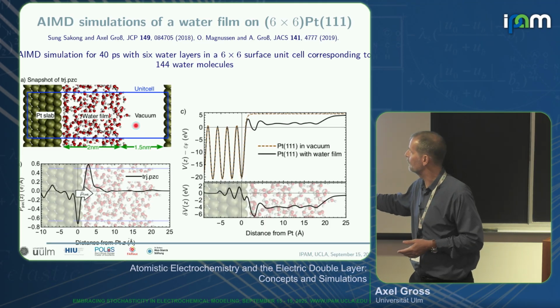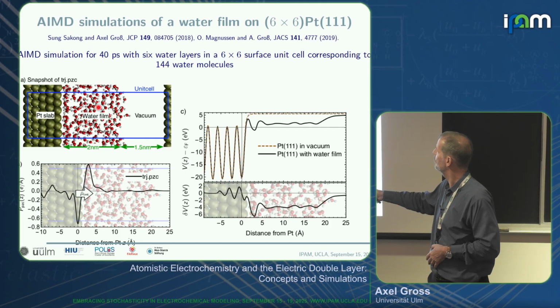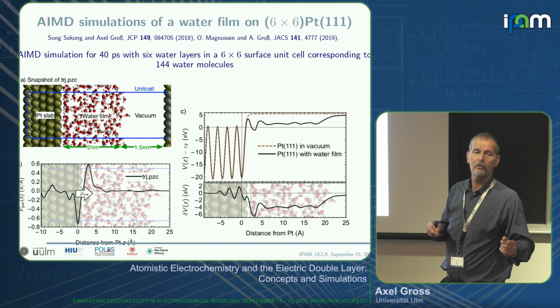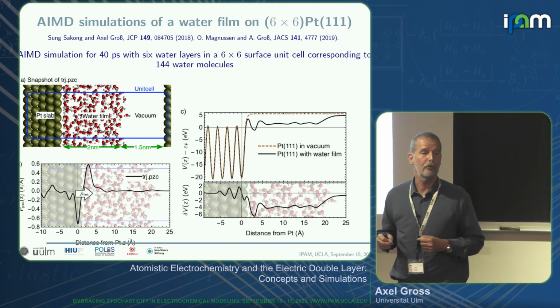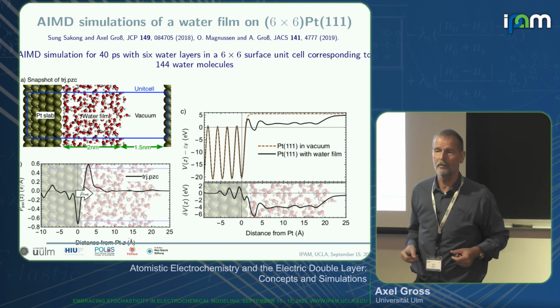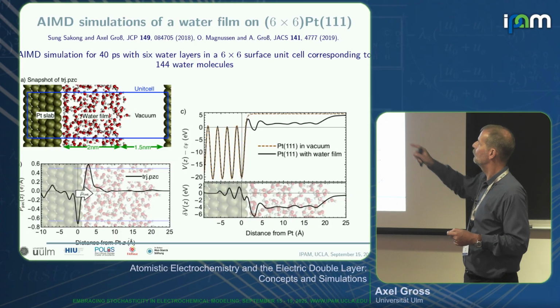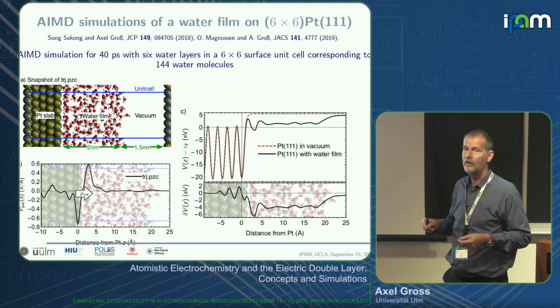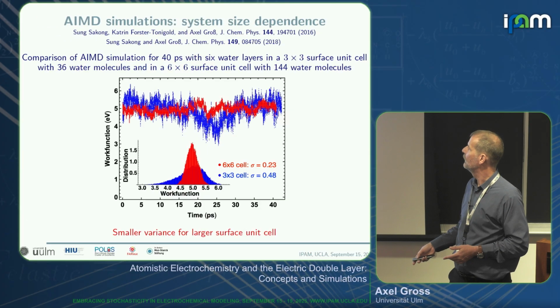So we have here 144 water molecules, and if we have one OH molecule, then the electron is immediately taken from the Fermi energy of the electrode, so this changes the Fermi energy. Or if we have an H3O molecule, it becomes automatically H3O+ and transfers its electron to the Fermi energy.